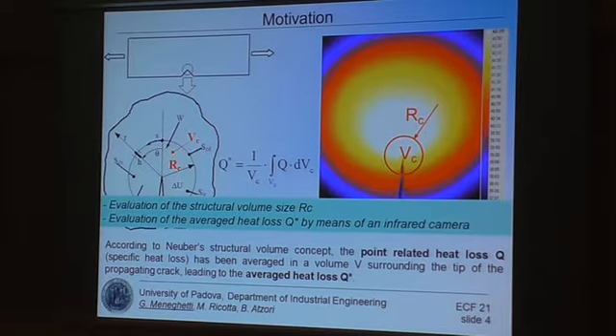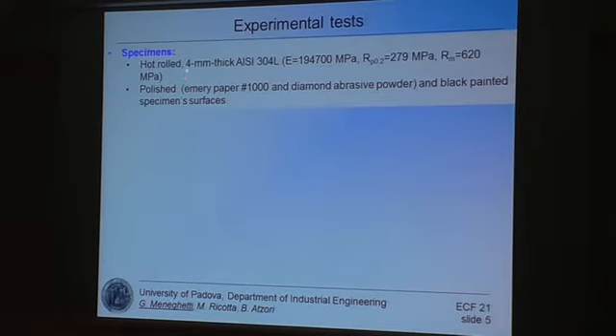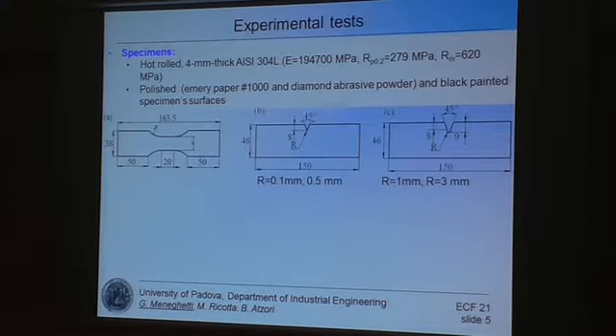So before showing you how to define the size of the structural volume and how to perform such integration, I would like to introduce the material we worked on in this paper. It is a hot rolled 4 mm thick stainless steel, low carbon steel. It had a tensile strength of 620 megapascal. We polished the surfaces in order to measure the energy dissipation with the infrared camera. The specimen's geometry is reported here.